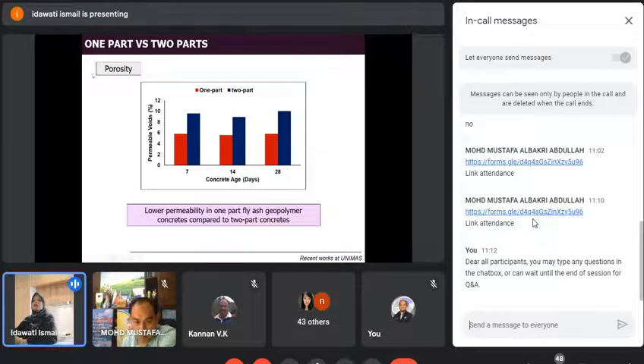So our work shows that in terms of porosity, one part geopolymer gives lower permeability. This is the volume of permeable void test, compared to two part. The value for two parts concrete. This is again our local fly ash with NaOH pellets. The two parts is mixed, I think this is 10 mole, 10 mole. Okay, and this is consistent with other publications that we found.